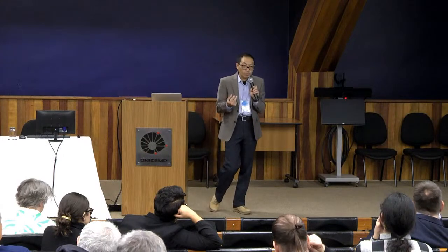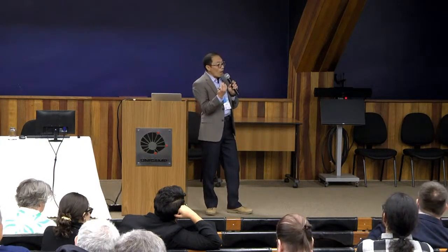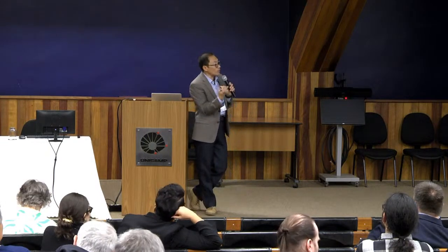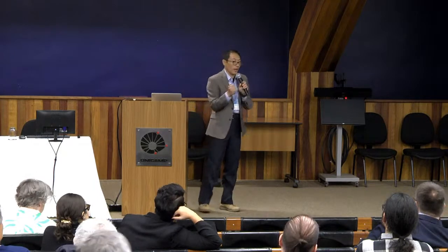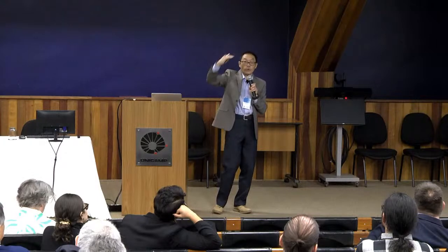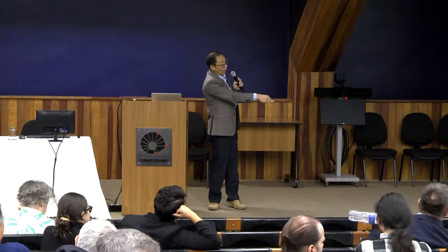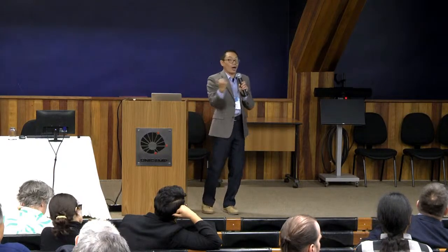Then there's a third domain of the model that is more fundamental. If you have a specific material called lithium rich, don't worry about the name, I have another slide to explain that, then there's a specific local structure with lithium, oxygen, lithium. Because lithium is highly ionic, your oxygen orbital along the lithium state gets highly unhybridized, so it gets lifted up close to the Fermi level. Of course, if you try to oxidize, in physics, oxidization is pulling out electrons. You start to pull out the electron from those lifted up unhybridized oxygen states, and then you oxidize the oxygen.